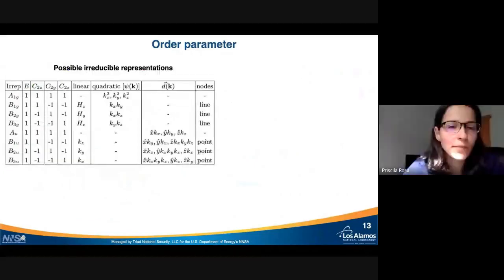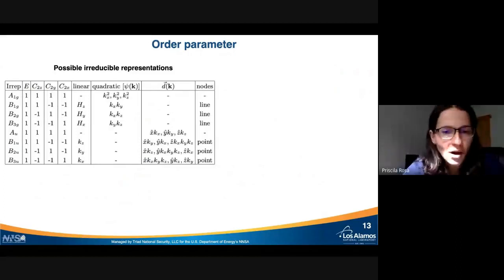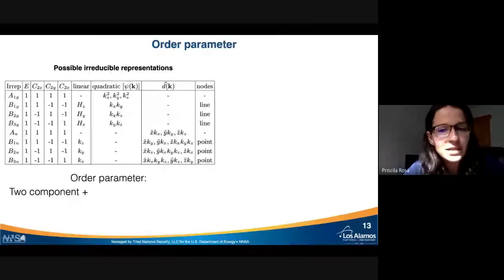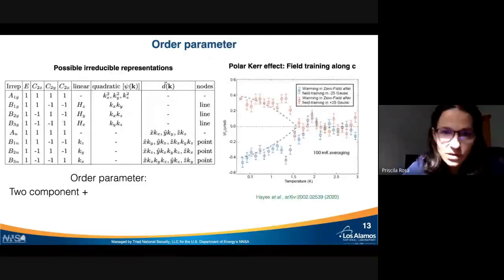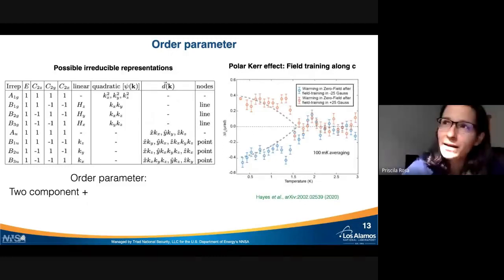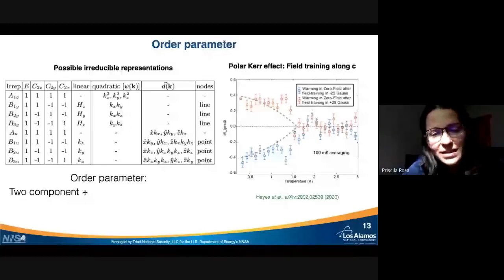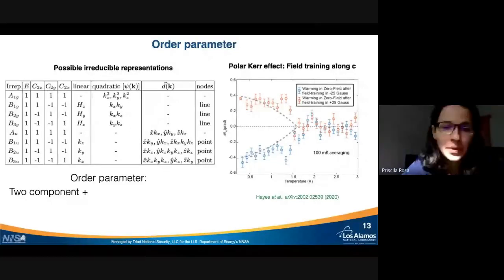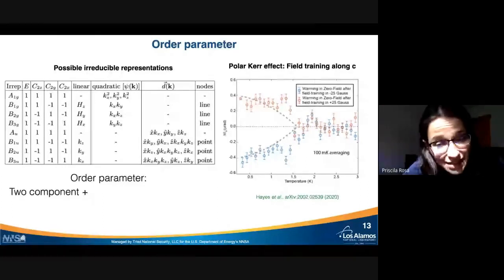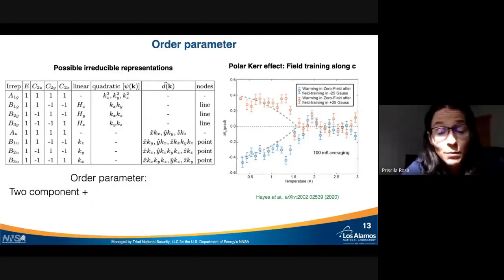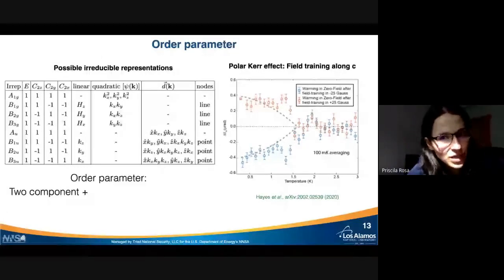One open question, though, going back to the possible irreducible representations, is that all sounds nice, but there is one problem here. So we know that the system is two-component, but there are recent results of polar Kerr effect. And without getting too much into the details, I can tell you that the polar Kerr effect gives evidence for time reversal symmetry breaking. So at 1.6 Kelvin here, there is a finite signal that implies that the superconducting state breaks time reversal symmetry. And moreover, this signal can be trained with magnetic field along the z-axis. So magnetic field along the z-axis means, if we go back to the table, a B1G symmetry of the system.